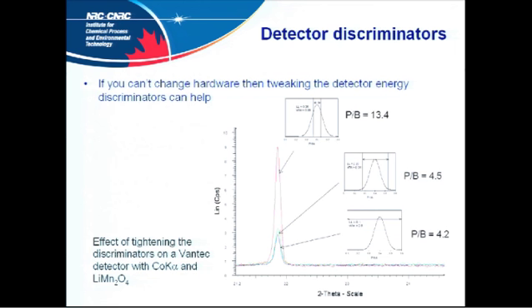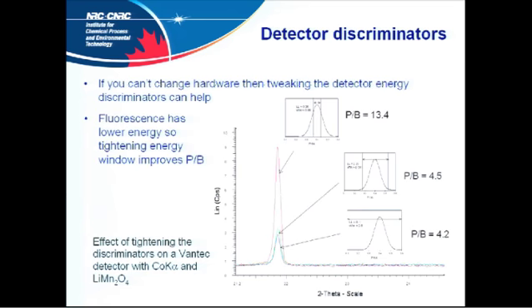Here, peak to background is 4.5 if you tighten it up a little bit. Tighten it up a little bit further, and you start getting something that looks a little bit better. Now, these peaks have been normalized to the background. So the one thing you don't see here is that you do suffer quite considerably in terms of the counts that you get, because you end up throwing away quite a significant amount of what you do want, along with the background. So it's very much a trade-off. It's worth spending a little bit of time finding the setting which produces the best peak to background whilst giving you as good a count rate as you can get.